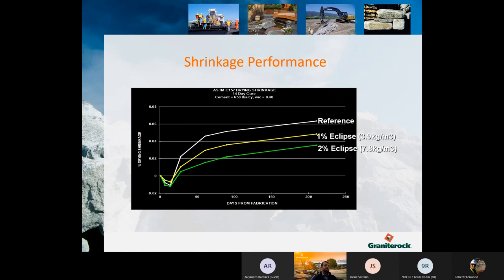Here's a small graph to show you that. Reference in white, 1% Eclipse in yellow, green is 2%. As you can see, the reference is about 0.06% at 14 days, and Eclipse can really cut that down. Most specs for low shrink concrete are around 0.04. So it really helps us provide mixes to meet shrinkage specifications.